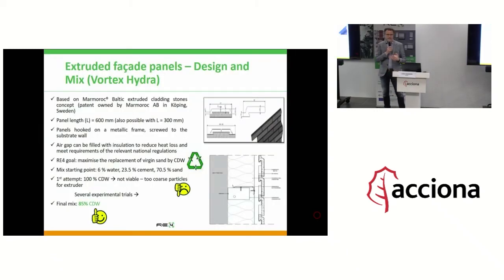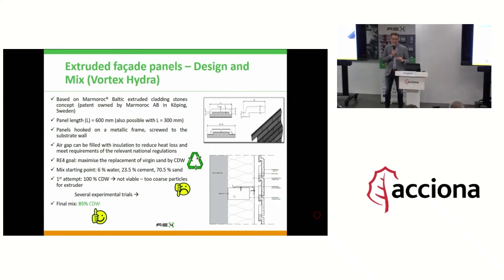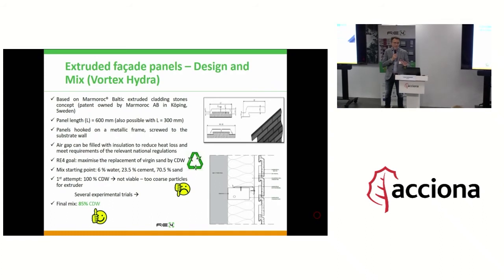This is based on an existing concept by Marmoroc in Sweden, with which Vortex have a commercial agreement to produce this. Since this is an existing system, the main goal in RE4 was to use CDW to replace the sand. In this concrete mix that is extruded as panels, roughly 70% is sand. The remaining is cement and water. So of the sand fraction,